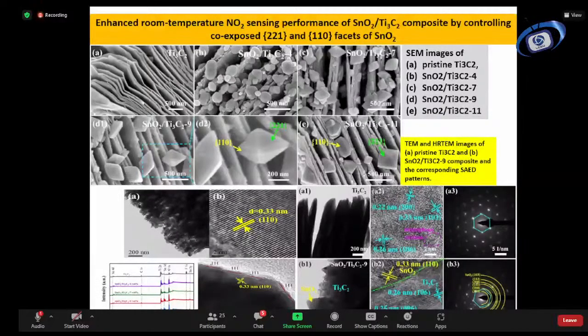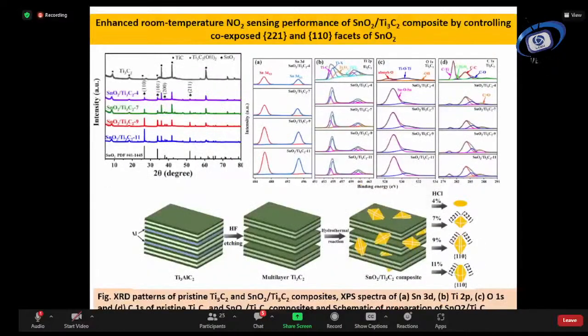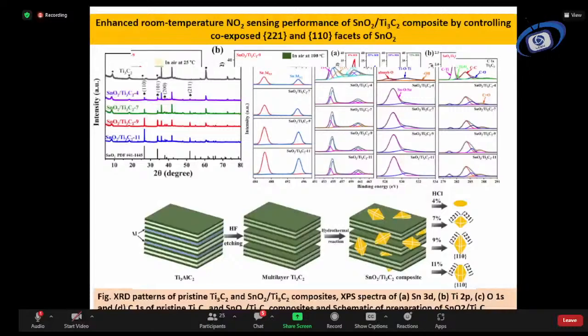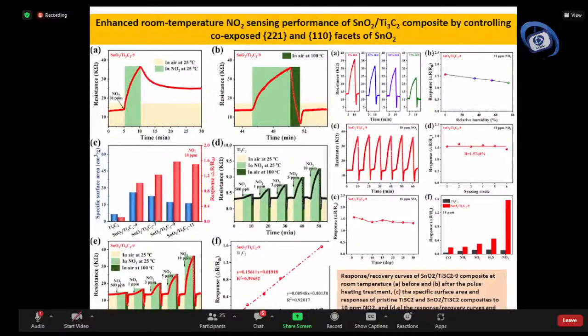And secondly, also XPS and typical XRD figures with different facets like 2 1 1 and other faces, because we focused on the 110 and also the 2 1 1 face. Because it is multifaceted, we tried to use double faces of a single nanomaterial to get multiple exposure of gas molecule interaction with the fabricated material. So we thought it could get a better response than the previous one. And it happened as well.